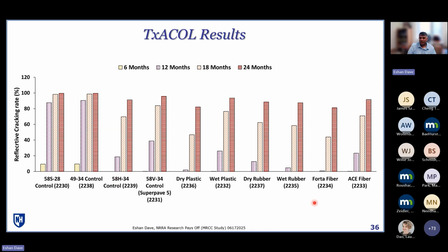versus if you look at some of these more modified mixtures, or mixtures that have fibers or plastic or rubber additives, they are performing better. You can see a slower rate of crack growth in those cases. For example, this fiber product had the best performance. Even when most of the other mixtures and controls had started to get to 100%, you were still well below that cracking amount.